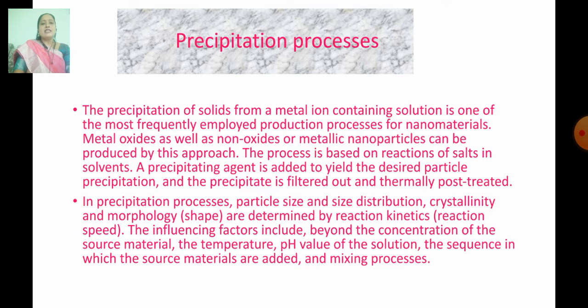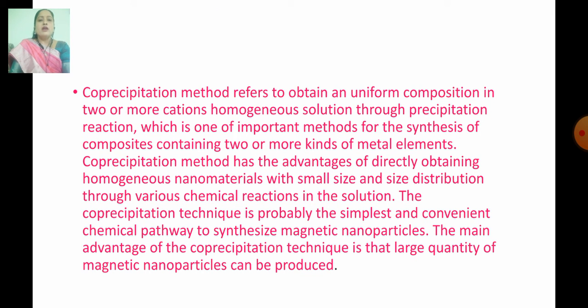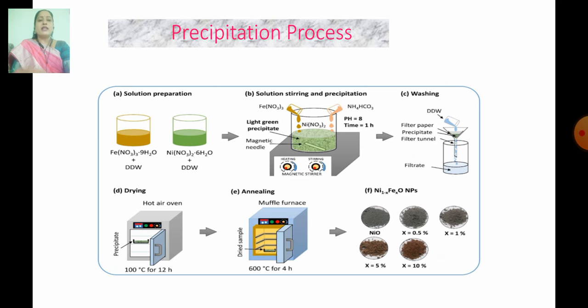In precipitation, particle size, size distributions and morphology are determined by reaction kinetics, and the influencing factors include the concentration of source material, the temperature, the pH value of the solution, the sequence in which the source materials are added, and the mixing process. Co-precipitation refers to obtaining a uniform composition in a homogeneous solution of two or more cations through precipitation reactions, which is one of the important methods of synthesis of composites containing two or more kinds of metal elements. This method has the advantage of directly obtaining homogeneous nanomaterials with small size and size distributions. This technique is the simplest and most convenient chemical pathway to synthesize magnetic nanoparticles.